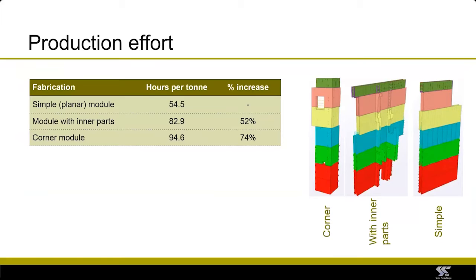Just a quick look at the fabrication effort required for these modules, and this is measured in hours per ton. For a simple planar module, so just a two-dimensional module, we were requiring on average 54.5 hours per ton. Modules that have inner parts, such as the picture in the middle, required 82.9 hours per ton. So that's 52% more than the planar module. And corner modules required the most in terms of fabrication time, 94.6 hours per ton, 74% more than a planar module.